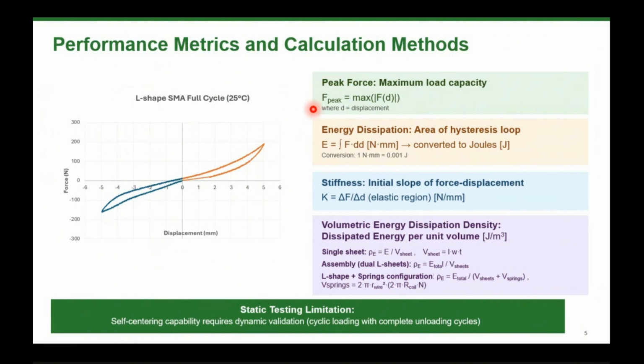And here I reported the definition of the key performance indicators that we will mention after. In particular, as performance indicators, we use the peak force, that is commonly the maximum load capacity, the energy dissipation, that is simply the area of the loop, the stiffness, that is the very first initial slope of the curve of force displacement, and the volumetric energy density, that is maybe the most important parameter